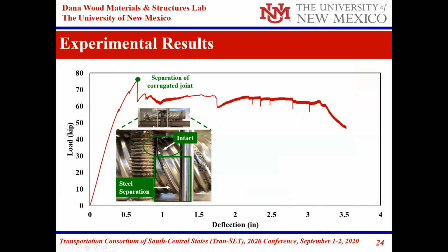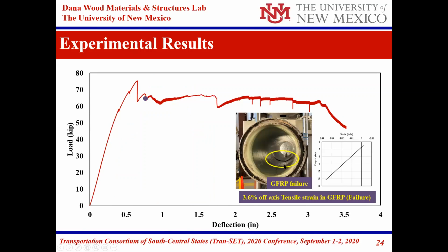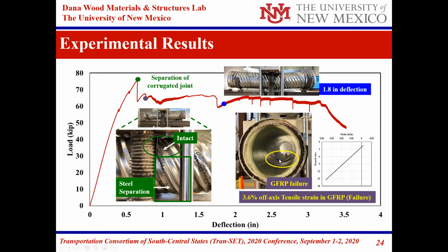And you can see basically the failures usually start at the corrugated joints with the corrugated metal pipe. Again, here you can see the failure points where you actually start seeing failure inside the GFRP itself, which means that the stress transferred and there is large deformation. And now the GFRP is the element that's taking the load, up to the point that the glass fiber itself fails. And that's where we stop the test, with the loss in capacity.